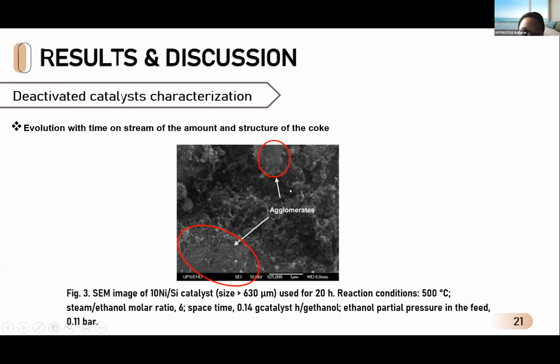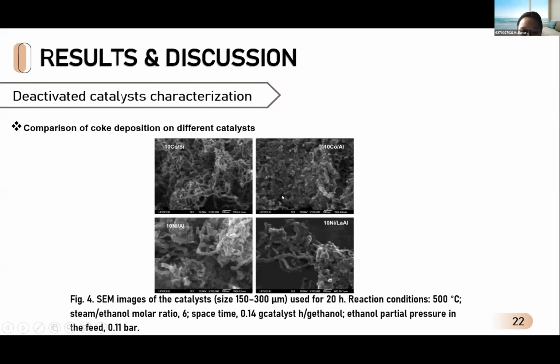Figure 3 corresponds to particles larger than 630 micrometers of the same catalyst used for 20 hours, and so they contain mainly filamentous coke on the outside. The content of carbon filaments is much higher than on the smaller particles, and accumulates, which makes it difficult to appreciate the nickel metal particle. Figure 4, for the different deactivated catalysts, confirms this filamentous structure of the coke, which is formed by coke filaments, highly heterogeneous in both size and shape.